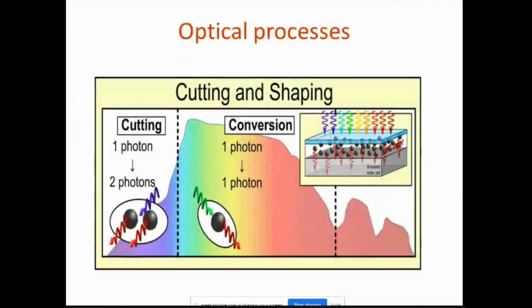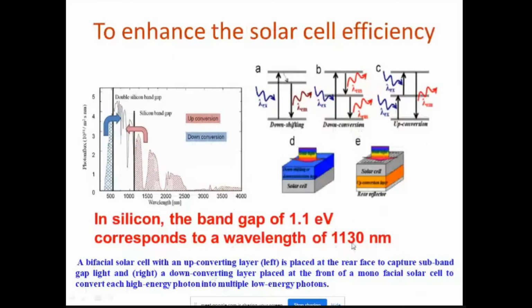Similarly, one more important part, for example, in solar cells, when sunlight falls on a solar photovoltaic cell, only around 1130 nanometers is utilized, absorbed, and converted to electricity. The remaining energy is unutilized. And now, if you are able to prepare a layer based on rare earth elements, high energy will be converted to lower energy, and lower energy will be converted to high energy. I mean, up conversion and down conversion. And now this is the portion absorbed by the solar cell, and this is the high energy that cannot be absorbed by the solar cell, and this is low energy that cannot be absorbed by the solar cell.